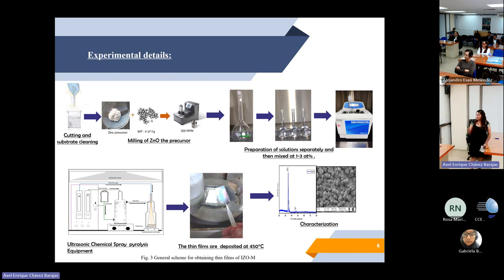Then the solution is sonicated for 10 minutes. Then the equipment, the ultrasonic chemical spray pyrolysis, is prepared with optimal conditions. Then the films are deposited at 450 Celsius degrees for 7 minutes. And finally, we make the characterization of the thin films.